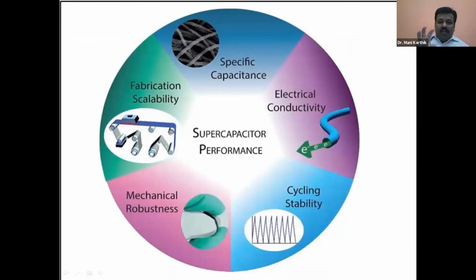Then, from the commercial point of view, the fabrication and everything is very important, because specific capacitance is very important. Electrical conductivity too, because when you prepare the material, we add activated carbon, that is the active material, and we need to add some conductive additives, for example carbon black, or binders. These three are uniformly mixed together to make the slurry, and we put it on the current collector, then only can we get very nice electrical conductivity. If there is no electrical conductivity, your rate capability will be affected. So that is a very important parameter for us.